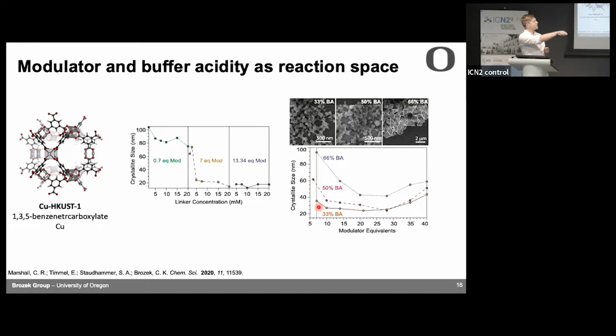And so we did something a little different. Rather than just add benzoic acid, we added it as a buffer. And so we varied how much of it was benzoic acid versus benzoate. And so this 33% benzoic acid here, that was a solution that was 33% benzoic acid, the rest was benzoate. And we see that for a fixed amount of modulator, you can control the size of the particles by using buffer synthetic conditions that are more acidic. And so if you increase the acidity of your solution, your particles are going to get bigger. And so we can control the size, but also the morphology. So this is all at the same equivalence of modulator, but we can control the size and morphology.